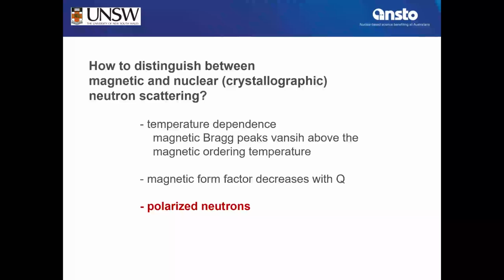A challenge is that we need to find a trick to distinguish between nuclear scattering and magnetic scattering, because as you have seen on a ferromagnet, the magnetic Bragg peaks appear on top of the nuclear Bragg peaks. And that's sometimes really tricky to distinguish because it could also look like a crystallographic phase transition. So we need to know, is that intensity of magnetic or nuclear origin?